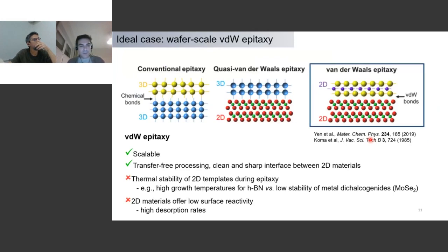I will point out two issues here. The first one is thermal stability. If you're growing a material on top of another, of course, you have to take into account growth temperatures. What do you need in order to get high crystalline quality and so on? One example: if I want to grow hBN on top of a metal dichalcogenide like molybdenum diselenide, no chance, this will not work, because at the temperatures I need for hBN, I will probably destroy the molybdenum diselenide, or it will get very defective because selenium will evaporate and so on. So there are these issues in terms of compatibility, what you can do.